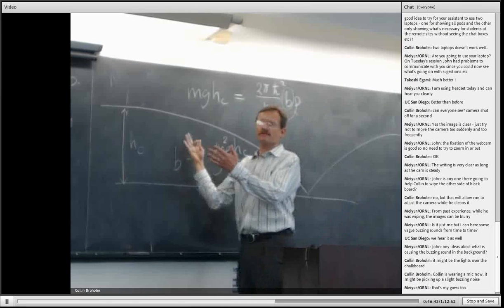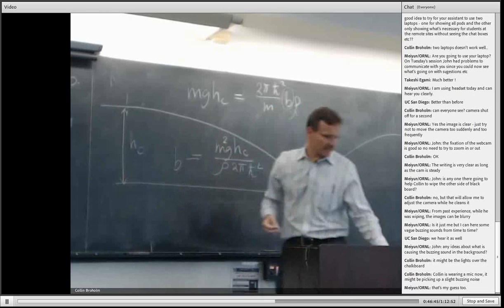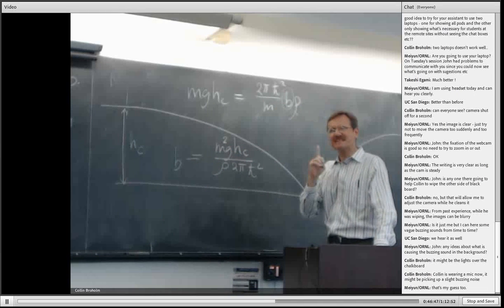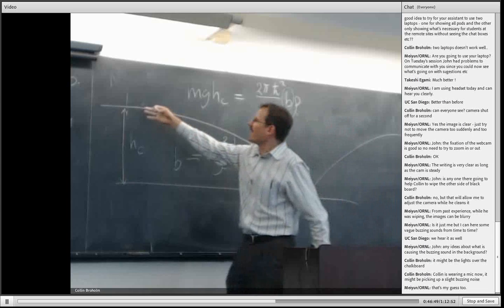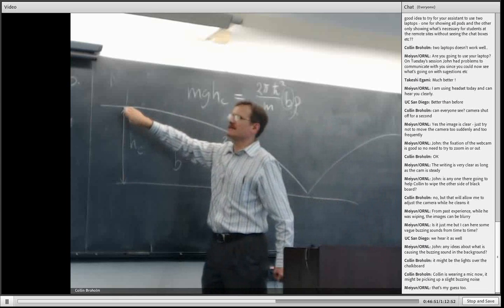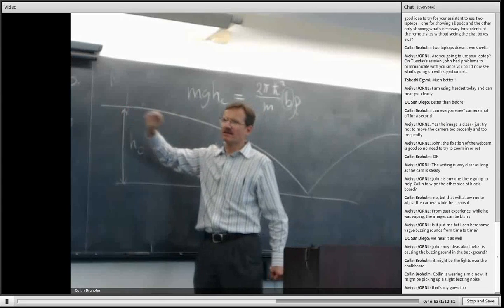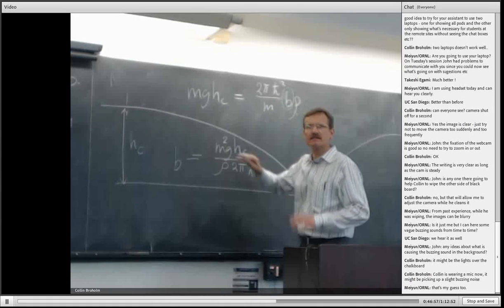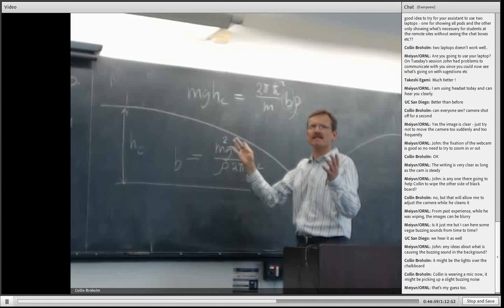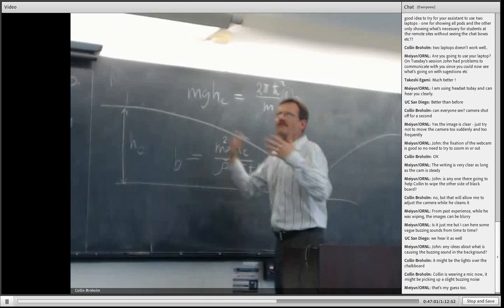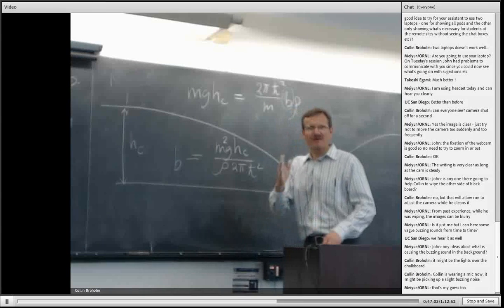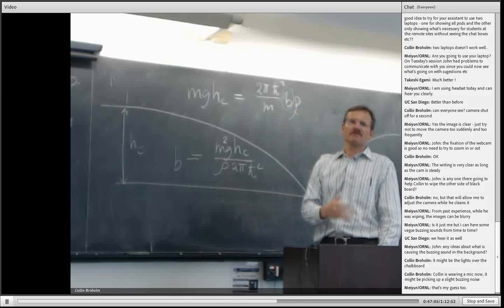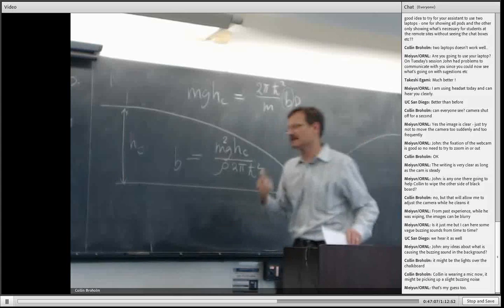And that's one of the ways that people use to measure these scattering lengths. It's also an example of a very clever experiment in which I don't have to monochromate the neutron beam. I don't have to make sure that they all have the same energy. It doesn't matter what energy they have, it's still this expression. So I can use a broad band of radiation, and that allows me to use more of the neutrons. And remember what I said, that the flux is always something we're really fighting with. So that's an elegant little experiment.